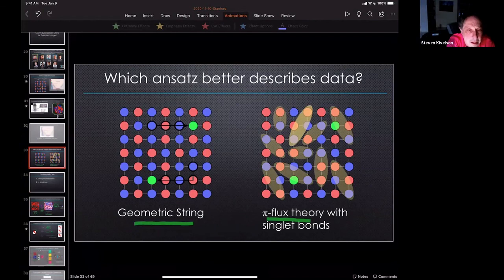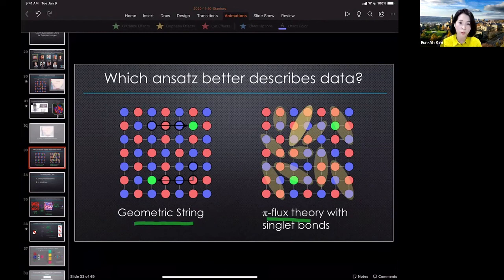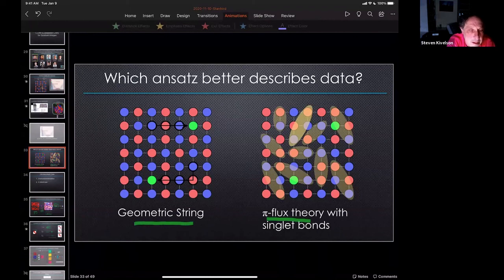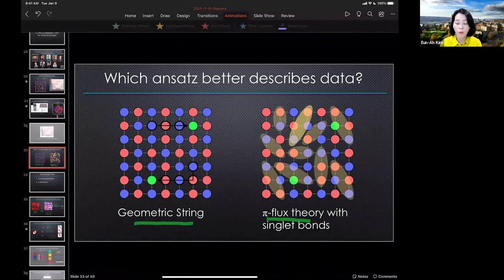You have these variational ansatz and you get the pictures out of them. The pictures look pretty similar to the experimental data. Both of them do, and neither of them have sharp features. They both look similar to an antiferromagnet because they are lightly doped. Beyond that, it's hard to tell. So maybe it's not very meaningful to try to distinguish them. Now my group's interest was more that you can train a neural network to distinguish these things. Turns out they were not that indistinguishable. You can ask whether they were meaningful tasks to test them with, but sometimes you cannot train a neural network to distinguish, you know, apple from apple.